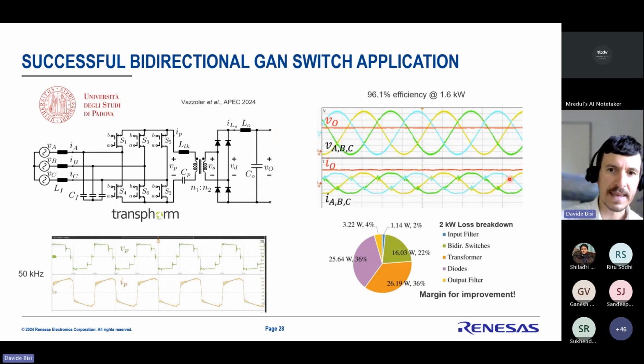And just to give you an idea of how it works in applications, we provided the bidirectional GaN switches to the University of Padova back in Europe, and they demonstrated this single stage AC to DC converter with the bidirectional GaN on the AC side. And you can see here 50 kilohertz switching with clean switching waveforms, and you can see here the AC input, which is 3-phase, and a very clean DC output. This was a 96.1% efficiency at 1.6 kilowatt, and there is margin for improvement in efficiency.